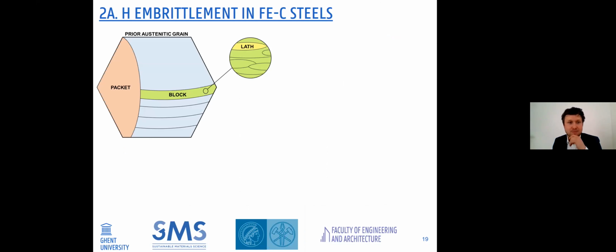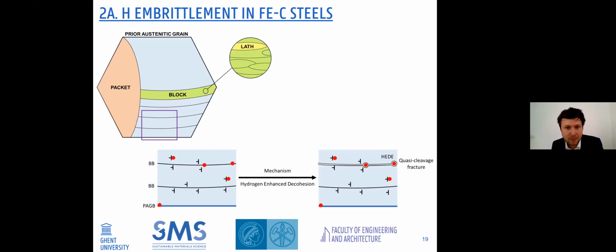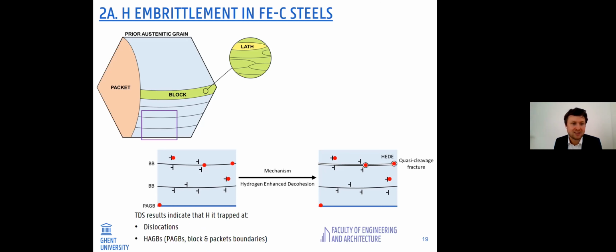If we go back to our system, you can see here the representation of the martensitic matrix consisting of prior austenitic grains. If we now focus on the block boundaries, what is really happening is a decohesion. Hydrogen can weaken the block boundaries and lead to quasi-cleavage fracture. This is a result, in the case when we have some plasticity, in the case of HELP, of both localized plasticity and concentration of hydrogen at packet or block boundaries, which are high angle grain boundaries, that also hinder dislocation movement. So this is the mechanism responsible for failure, because TDS indicated that hydrogen was trapped at dislocations and high angle grain boundaries, and then the packet and block boundaries were the weakest link.